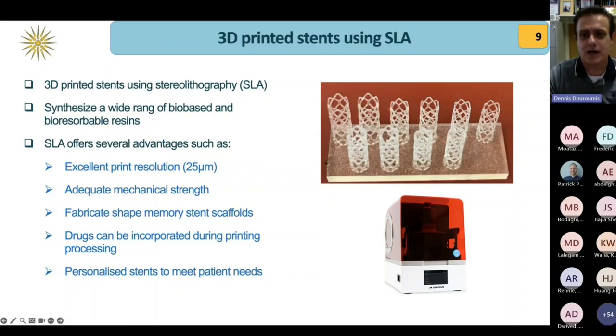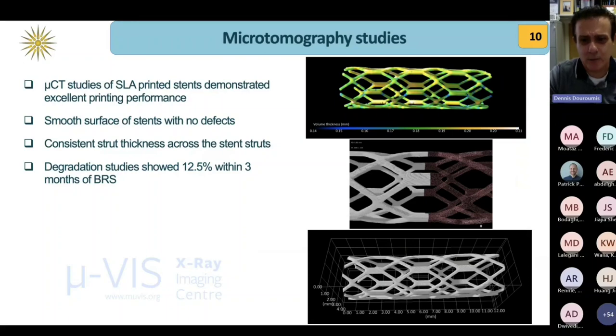Eventually, as you can see on the top image, we could print a wide range of different shapes, designs, or dimensions of the stent. But what was important for us was that the thickness of the strut could go below 300 micrometers. We could have easily 150 micrometers or 200 or 250. And then another benefit was that the surface was very smooth, and we didn't have to do any post-processing work.